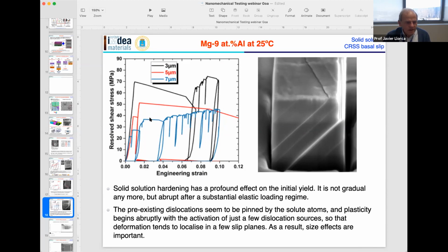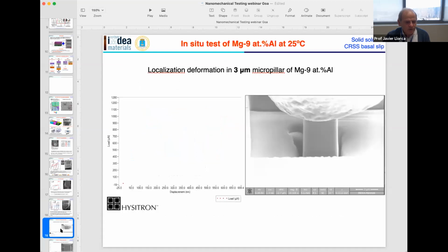If you want really to see this localization effect and see how the deformation progresses, then you can go to the in situ test. So what you are going to see here is a movie of an in situ test of a micropillar of magnesium 9 atomic percent aluminum with a size of 3 by 3 microns, where you are going to see the localization of the deformation. So this is the load.